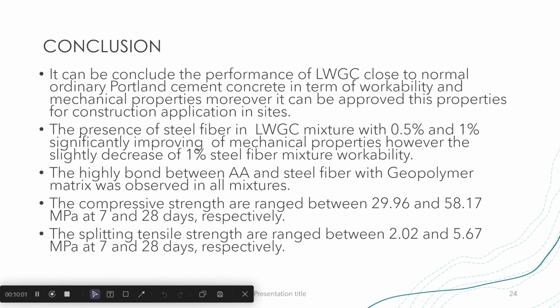Fourth, the compressive strengths ranged between 29.96 and 58.17 megapascal at 7 and 28 days respectively. And finally, the splitting tensile strengths ranged between 2.02 and 5.67 megapascal at 7 and 28 days respectively.